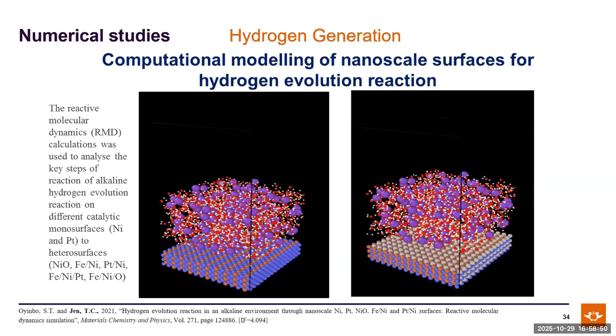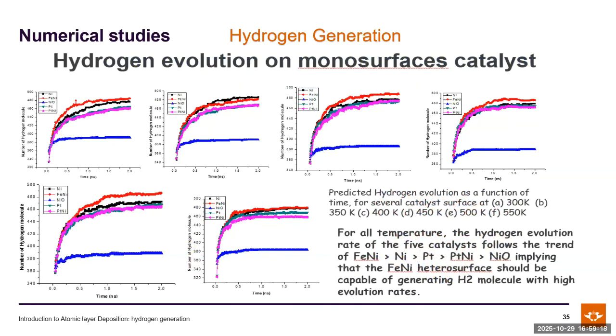So I have these surfaces: nickel oxide and nickel iron composite, platinum nickel composite, iron nickel platinum composite, and iron nickel oxide. We do this kind of reactive molecular simulation, and this gives us some intuition and an idea of what is the best one. It's very intriguing. Here it is ABCD, but we just look at the simple one.